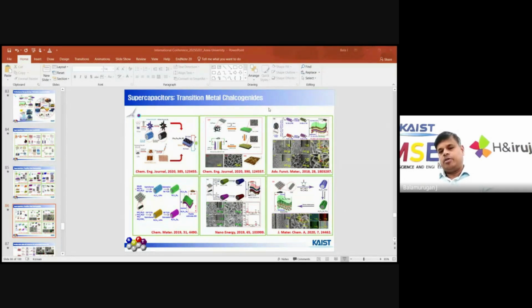After the carbon cloth, we use both positive material and negative material. After fabricating the positive and negative material, we studied them by morphological investigation and electrochemical test performance. And finally, we make the device to achieve high energy density, power density, and high durability, especially long-term cycle stability. So based on the metal sulfide and metal sulfide selenide based material, we grow on the carbon cloth.